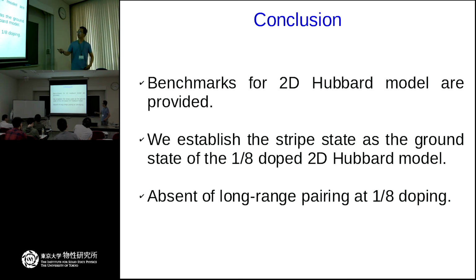So here comes my conclusion. In the calibration of many-electron problems, we provide a benchmark for the two-dimensional Hubbard model. This is very useful if you want to develop new methods, or if you want to look at the strengths and weaknesses of existing methods. We establish that the stripe state is the ground state of the two-dimensional Hubbard model. And it seems there is no long-range pairing at this doping. I want to emphasize that because we studied the pure Hubbard model, the absence of long-range pairing in our calculation indicates that if you want to have long-range pairing in the Hubbard model, you might need to add some other terms, for example, the t-prime hopping term, into this model.